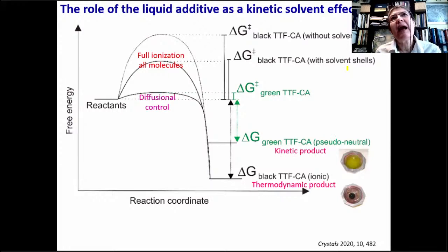So I have interpreted this liquid additive role as similar to a kinetic solvent effect. We can say that the green tetrathiafulvalene chloranil product is typically obtained first, and the formation of this material may be under diffusional control. It's only necessary that those molecules meet, and very easily this material, the green form, is obtained.